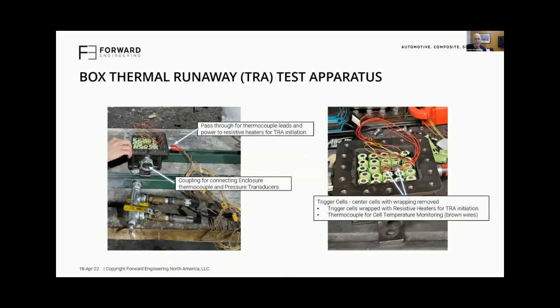Here's a dive inside the enclosure. You can see that array of cells. These 2 center cells are wrapped with a thermal resistive heater. Power lines run to that, which gradually at X degrees per minute bring the temperature up of those cells and initiate thermal runaway.